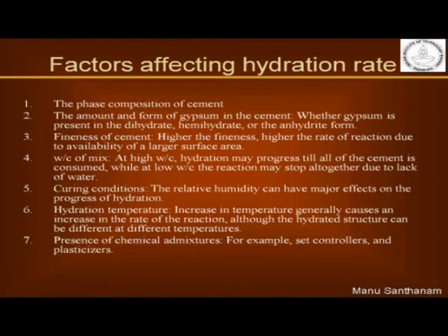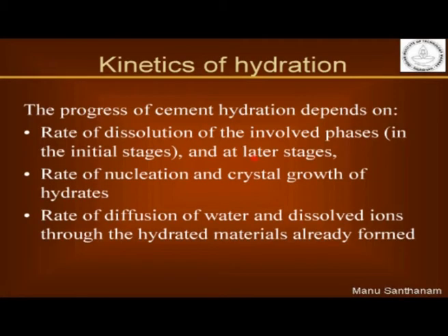So if you go back to the previous slide, temperature is one thing that is probably going to affect all these 3 things. It is going to affect the rate at which dissolution happens. Dissolution will be faster in the presence of high temperature. The rate of nucleation and crystal growth will increase, and the rate of diffusion of water also will increase when you increase the temperature. So again, temperature affects the rate of reaction the greatest.